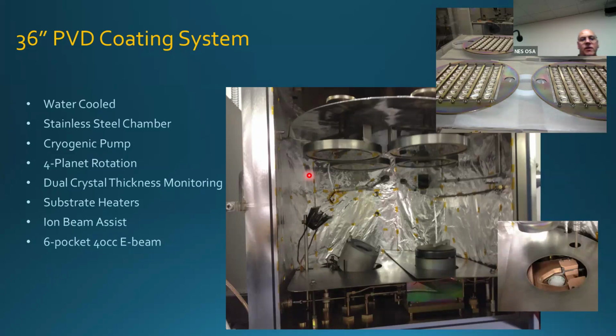We monitor the thickness of the coating as we're depositing with two crystal sensors. In this case, there's one in the center and one here on the edge. And we average those two. The film that's condensing on the sensor is not exactly the same film thickness that's on the substrate, but we qualify the system by determining a tooling factor, the ratio of what condenses on the crystal to what is condensing on the substrates. And that's programmed into our deposition controller. And that stays with that system as long as we don't change the geometry of the chamber.